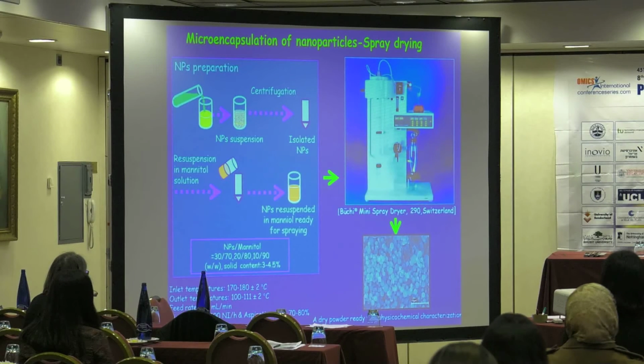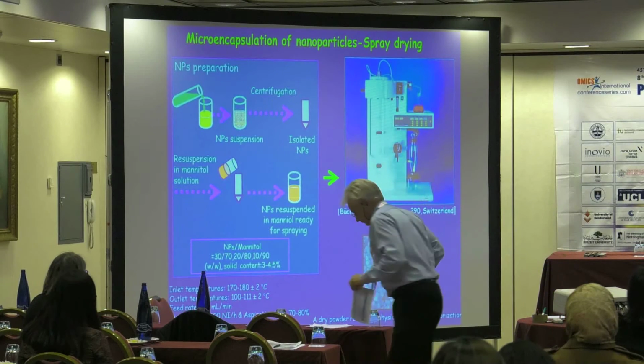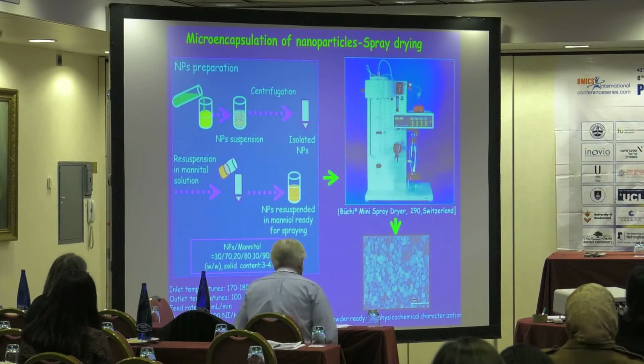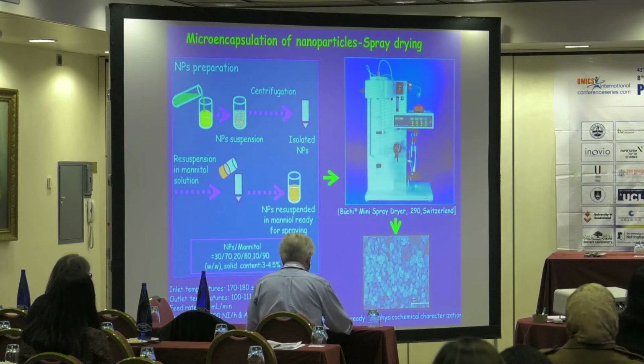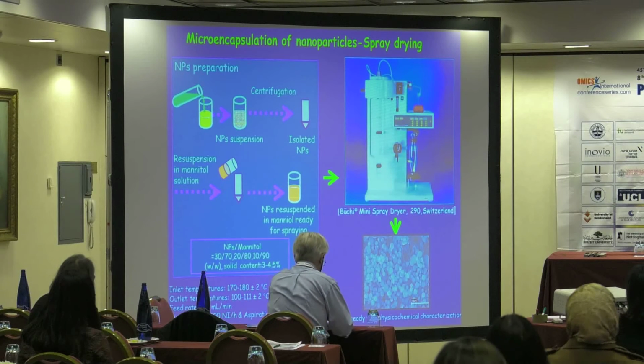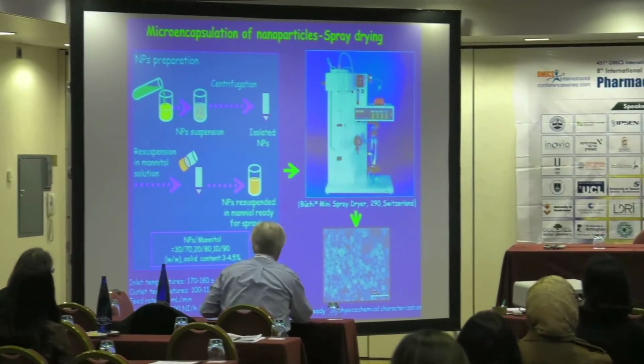We add different concentrations of mannitol and mix them under drying at room temperature. We used different concentrations of mannitol relative to the nanoparticles, with 30 to 70, 20 to 80, and 10 to 90 weight ratios of nanoparticles to mannitol.